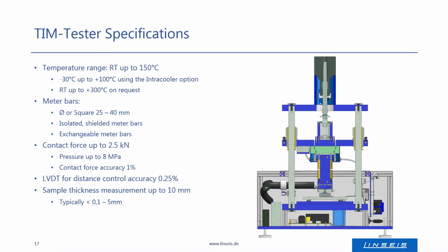With the LVDT, one can measure the sample thickness. The accuracy here is about 0.25%. Typically, one can measure samples in the thickness range of up to 10 millimeters, and the most investigated sample thicknesses are in the range of 0.1 to 5 millimeters.